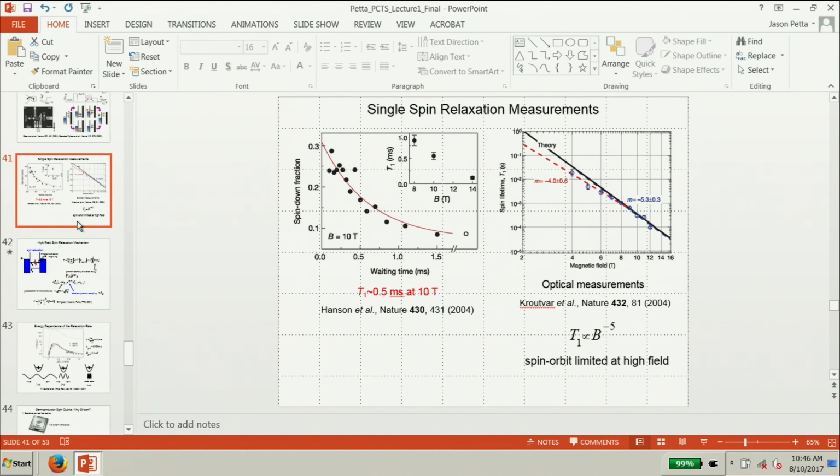But now in silicon, we have this isotopic enrichment, which is very good in terms of coherence. And a lot of what our group has been battling are materials challenges and fabrication challenges because there's no Loren Pfeiffer for silicon. There's no well-developed MBE growth process for these silicon germanium quantum wells. And we had to work that out, and that takes time. But now that the quantum wells work, and we have these new gate designs, it looks quite good in terms of single qubit and 2-qubit gates.